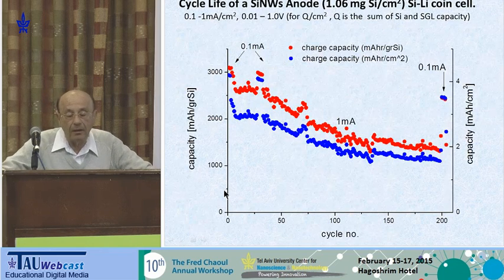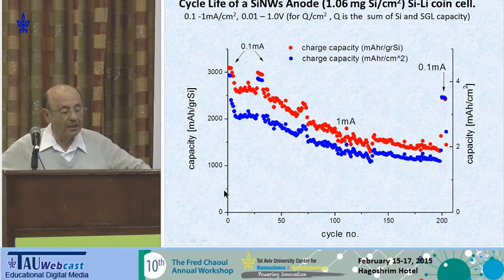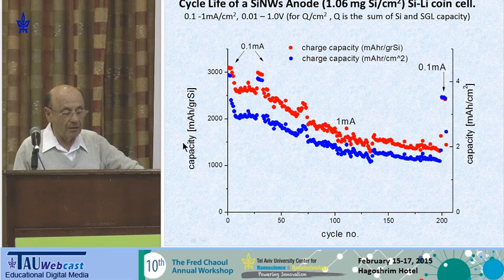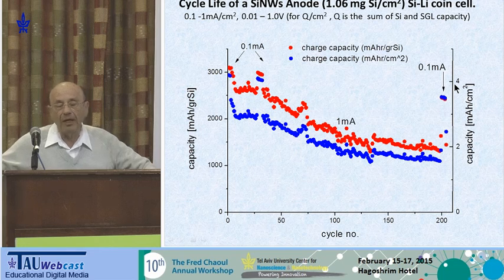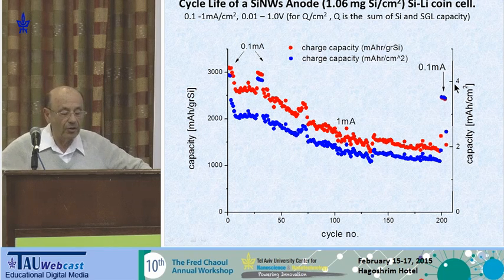We tested the electrochemical behavior of these anodes. We built what we call in electrochemistry half cells, silicon nanowires versus lithium, and cycled them, and then a complete battery. What you see here is the capacity in terms of milliampere hour per gram of silicon versus cycle number. So we cycled 200 times. And here is the capacity in terms of milliampere hour per square centimeter of electrode area, and we got about 4. This is very important. There are many papers in Nature and Science and others showing excellent performance of silicon nanowires, but they're using 0.1 milliampere per square centimeter. So it's very good to write a paper. It is nothing for a real battery.